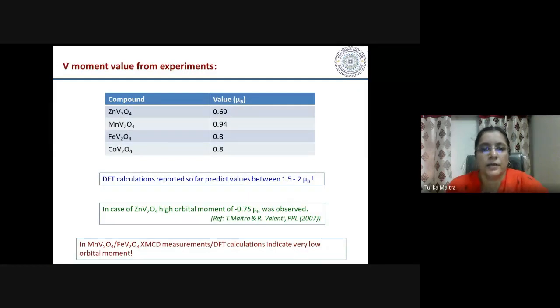So there are 2 important issues which need to be resolved here. One is that in these spinel vanadates, the magnetic moment of the vanadium ion is much smaller than expected, 2 mu b, which is expected theoretically for a V3 plus state. If there is V3 plus state, then there are 2 electrons present, so it should be 2 mu b. But we see in experiments that the moment is found to be much lower, even lower than 1 mu b. So it is not understood why this is so low. If we do traditional DFT calculations, then we find that the moment comes out to be around 1.5 to 2 mu b.